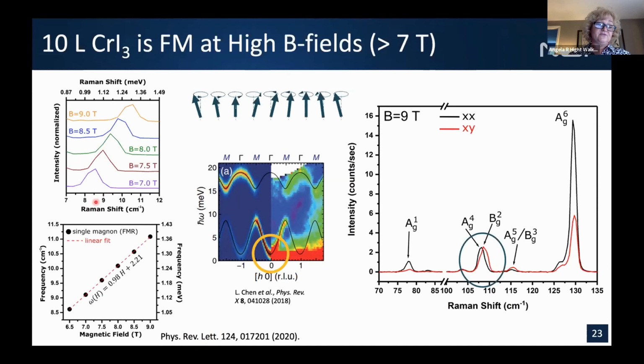What's interesting is it's very close to 0 without magnetic field. So the only way we can see it is by applying our magnetic field and watching it shift with field. This is only the positive side of the split feature. The negative side, of course, is beyond our capability to see in low frequency. So this is, in fact, a magnon.